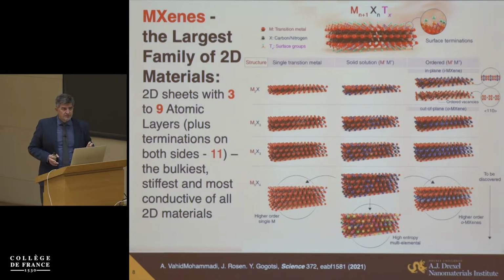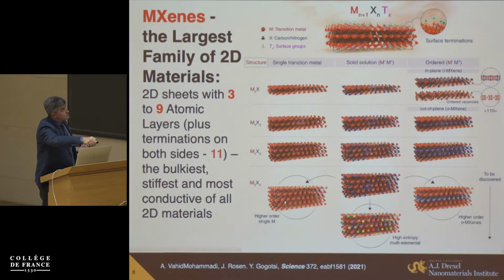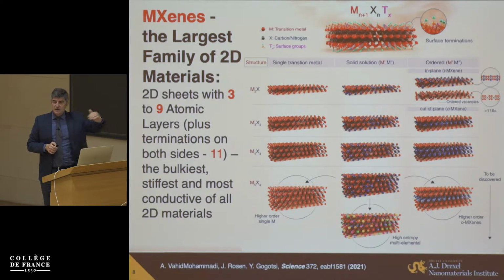You can find something similar in the world of materials in metal organic frameworks or covalent organic frameworks, where you can play with organic groups and elements and create a variety of structures. Similarly here, we can make M2X, M3X2, and so on, structures with up to 5 layers of transition metals. We can make atomic sandwiches where one atomic layer of molybdenum is on the surface and titanium, 1 or 2 layers, is in the middle. We can make in-plane ordered materials with atomic columns alternating different elements, and if you etch one of them, like yttrium or scandium, away, you can end up with atomic column regions, like double vacancy rows on the layer. So you can imagine, it's certainly just the beginning here.